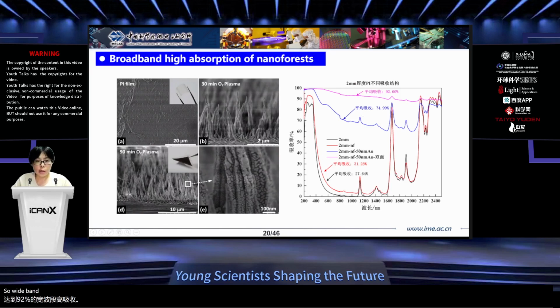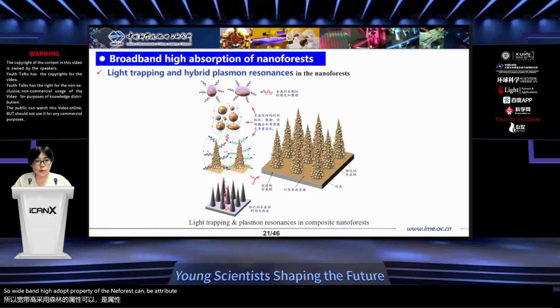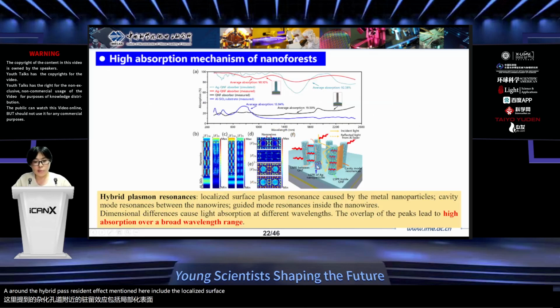The wide band high absorption property of the nanoforest can be attributed to two effects. One is the light trapping effect of the nanoforest, since they have a large aspect ratio. The other is the hybrid surface plasmon resonance effect. The hybrid plasmon resonance effect mentioned here includes the localized surface plasmon resonance caused by the metal nanoparticles, the cavity mode resonance between the nanowires, and also the waveguide mode resonance inside the nanowires. Due to the different sizes, distribution, and spacing of the metal nanoparticles and the nanowires, each size and distribution corresponds to a separate absorption peak.